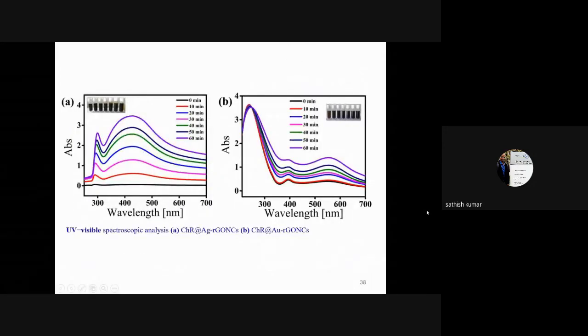In the case of the nanocomposites, we have used silver nitrate and gold chloroauric acid for the synthesis of silver nanoparticle decorated graphene nanosheets, as well as gold nanoparticle decorated nanosheets. Decorated means the hybridization process. The hybridization is broadly categorized into two types: one is ex situ hybridization and another one is in situ hybridization. I don't want to discuss the hybridization process elaborately because it will be confusing.